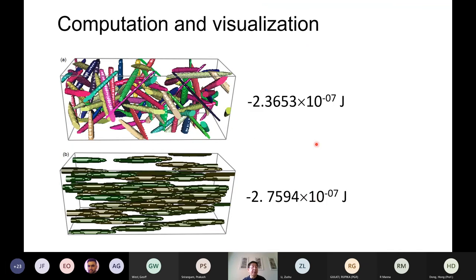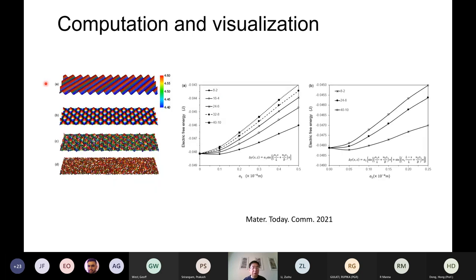So we can really tell how the temperature inside the inclusion will change. Visualization is important. We also calculate inclusions that are fibers or needle-like, like carbon nanotubes, put into a conductive liquid like salted water, and look at the free energy difference. This is a randomly distributed fiber, and we calculate the free energy of the system as this. After they are aligned, the free energy is reduced to this. So the electric field can help to align fibers or needle-like morphologies. That's another type of calculation.